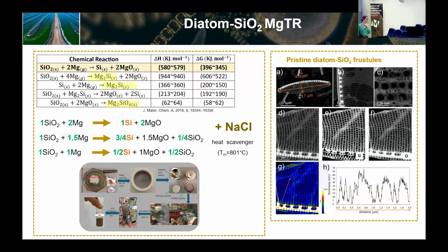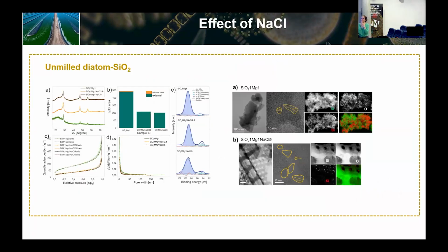So this is species A, as I told before. This is from EELS, actually, some idea of the thickness of the frustule. These are just a few nanometers thick. And we first try to do this SiOx reduction in the bulk material, the SiO2. So these are the first results. If you see, this is 1:1, 1:1.5. No, sorry, this is 1:1, but with different sodium chloride contents.